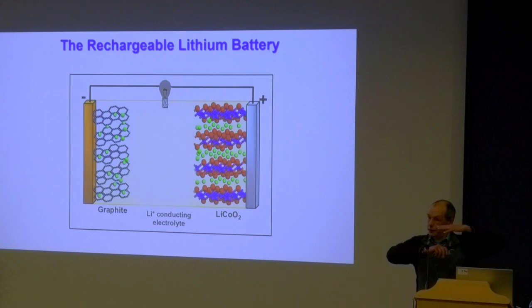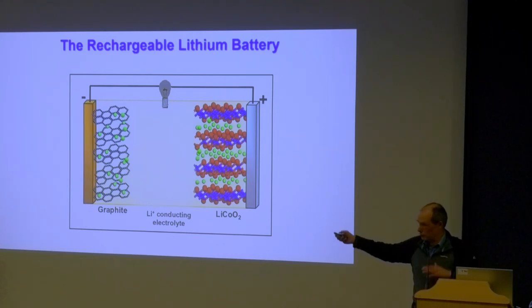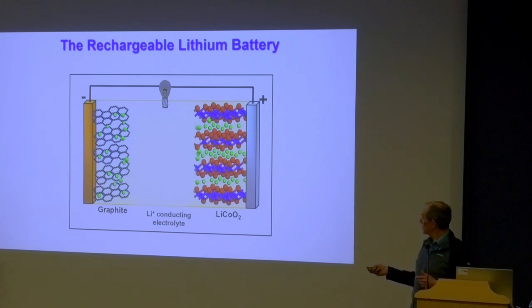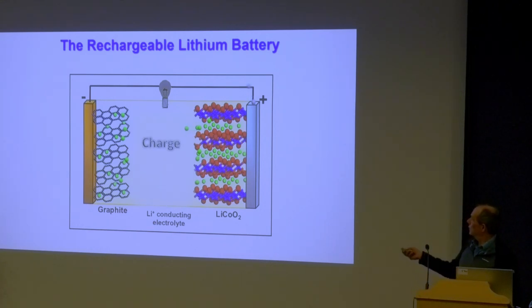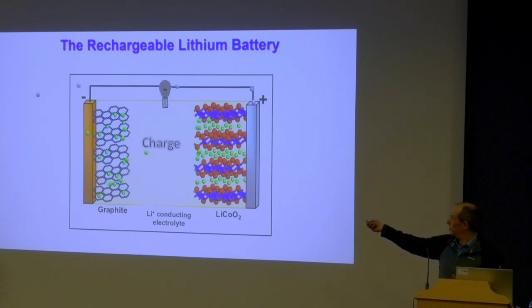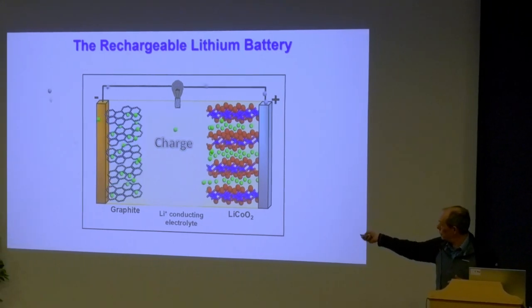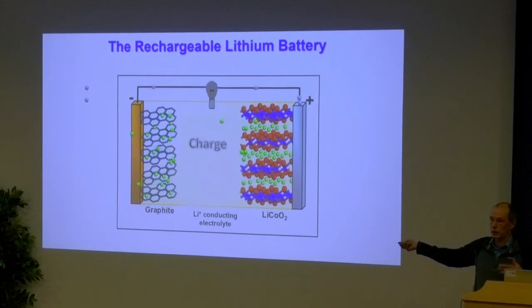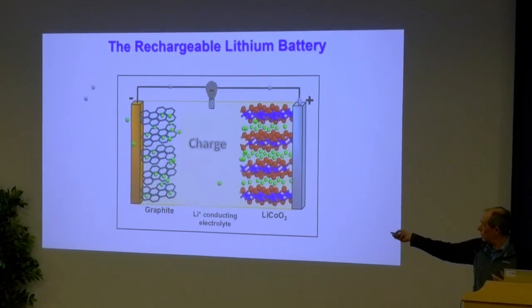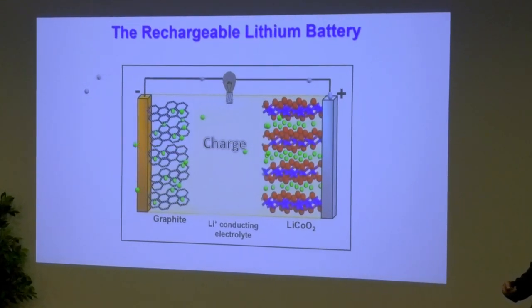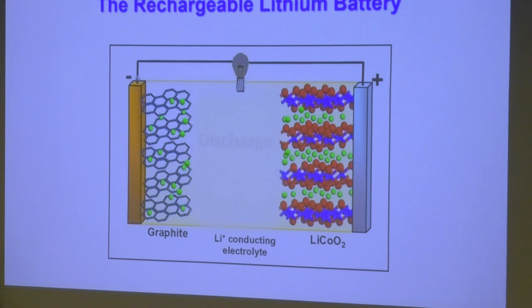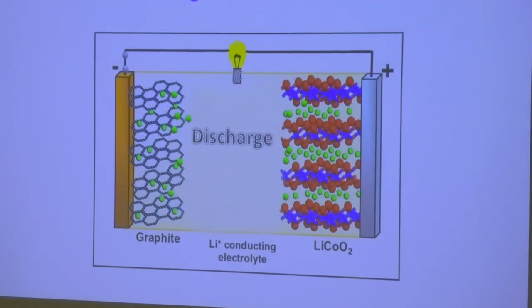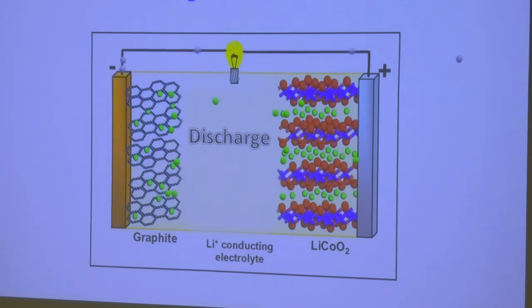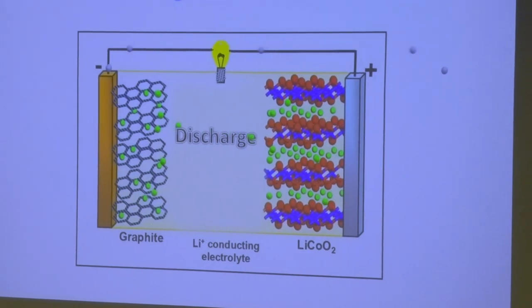We have graphitic carbon as the negative electrode, so sheets of carbon, and when we charge the battery, lithium ions come out from between the layers of the lithium cobalt oxide. They pass through an organic lithium ion conducting electrolyte and they go between the layers of the graphite. Then on the discharge, when we're using the battery to get energy from it, the reverse happens. So it's a very nice reversible bit of chemistry, what we call two reversible intercalation reactions.